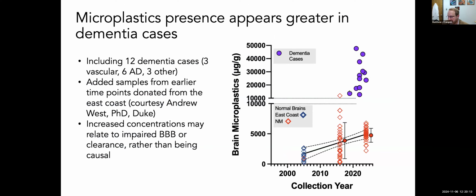This is all in preprint right now, and we're responding to reviewer comments. And one of them was, well, you need to show us more data at a different time point. So we were able to get East Coast samples, so geographically different. There are many differences with these East Coast samples shown here in blue compared to the New Mexico samples I just showed you, but you can see that by and large they are lower. There's this consistent trend here.